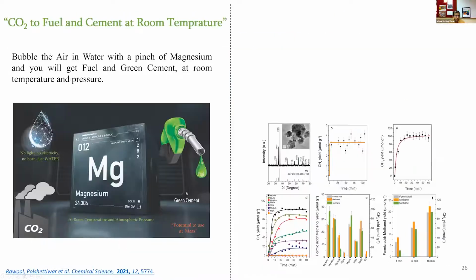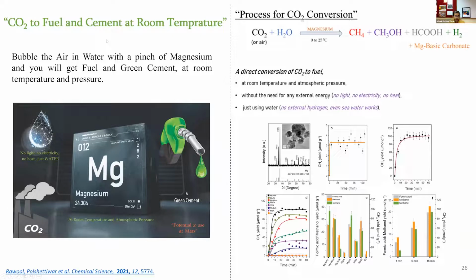We also showed use of magnesium to convert CO2 to fuel: CO2 to methane, methanol, formic acid, and cement. This works at room temperature. Don't need any hydrogen source, just water. The only drawback is the magnesium gets converted into magnesium basic carbonate, which has its own value. It's a value-added product. However, we're now trying to see whether I can regenerate the magnesium back from magnesium basic carbonate.